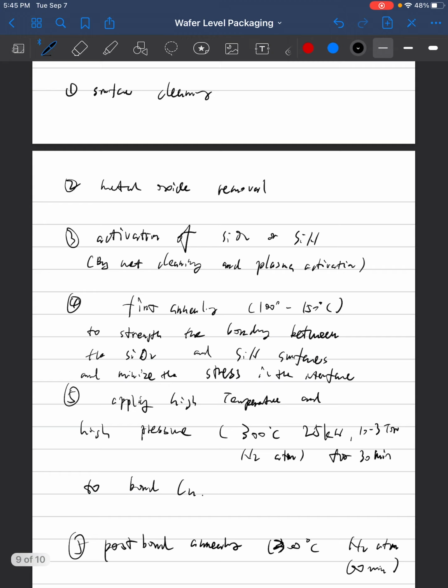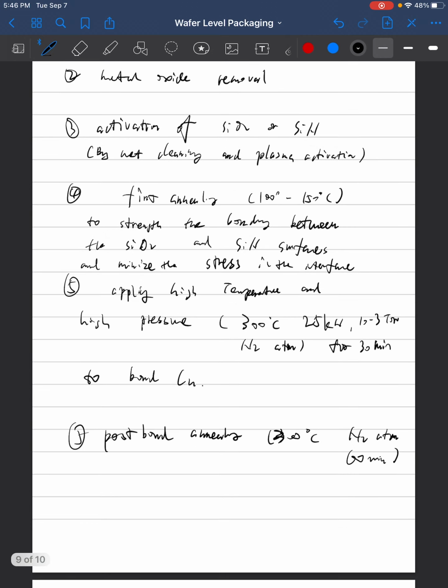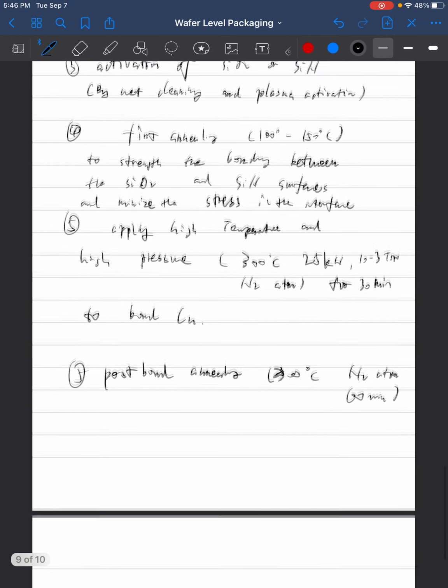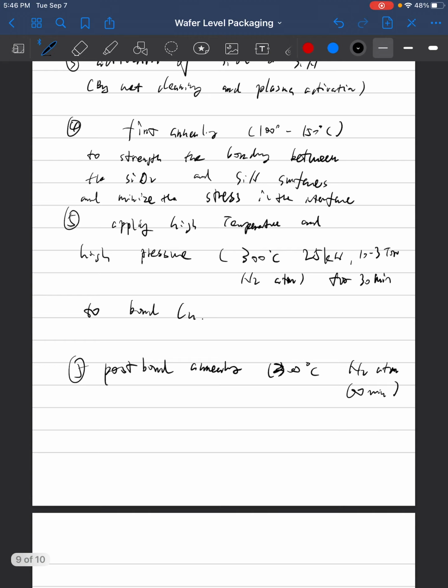Then we apply a higher temperature and higher pressure. Usually it's like 300 Celsius degrees at 25 kilonewtons in nitrogen environment for 30 minutes to bond the copper pillars. After that, we do some post-bond annealing at 300 Celsius degrees, also in nitrogen environment, for 60 minutes.